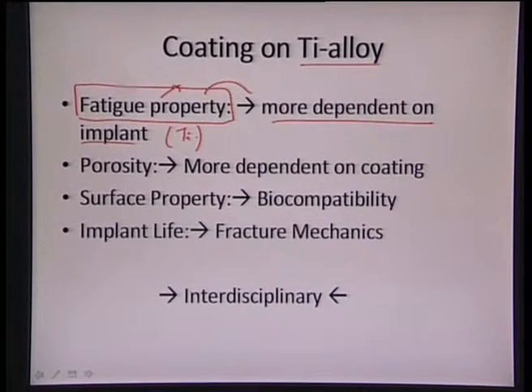So if you are utilizing commercially pure titanium, it might have a fatigue strength of around 300 megapascals at 10 power 7 cycles. But if you take a titanium alloy and properly heat treat it, it can have up to 600, 700 MPa for the same life cycles. So that essentially tells us that we have to utilize a superior grade of titanium if we want to achieve very high or enhanced fatigue properties, and that is mostly dependent on the implant, because the implant is the one which has to take the overall load.